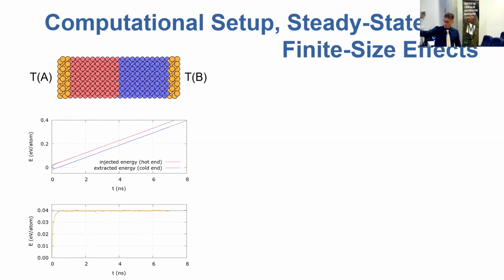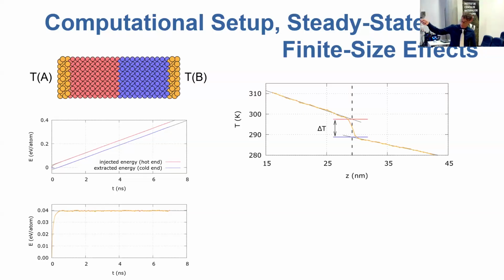Here you can see that there is a pretty clear steady state window, meaning that no additional energy is injected or removed from the system as a whole. We could select a steady state window, which goes roughly from 2 nanoseconds up to 7 nanoseconds. And within this steady state window, we averaged the instantaneous temperature of the ions, and we derived the steady state temperature profile of the junction, which is depicted in the plot there. From it, we performed a linear fit on the left and on the right of the interface.